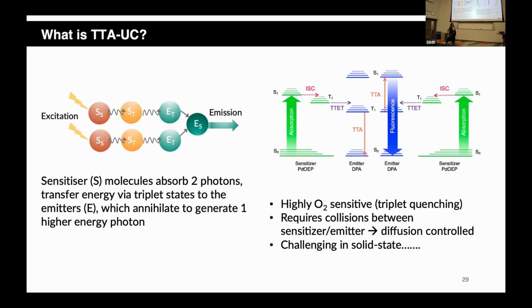So the key things about this process are that it's highly oxygen sensitive. There's loads of triplet states here. Ground state oxygen is a triplet, so triplet quenching is a problem. The second issue is we need collisions between our sensitizer and our emitter. Okay, it's a diffusion controlled process. So trying to do this in the solid state is actually really challenging.